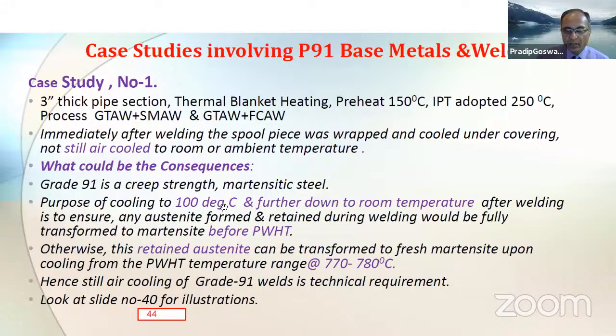The purpose of cooling to 100 degrees centigrade or further down to room temperature after welding is to ensure any austenite formed and retained during welding would fully be transformed to martensite before post-weld heat treatment. Otherwise, this retained austenite can be transformed to fresh martensite upon cooling from the post-weld heat treatment temperature, which is typically 770 to 780 degrees centigrade. Hence, still air cooling of grade 91 steel is a technical requirement.